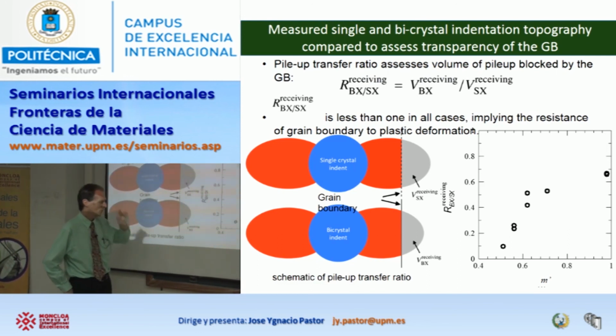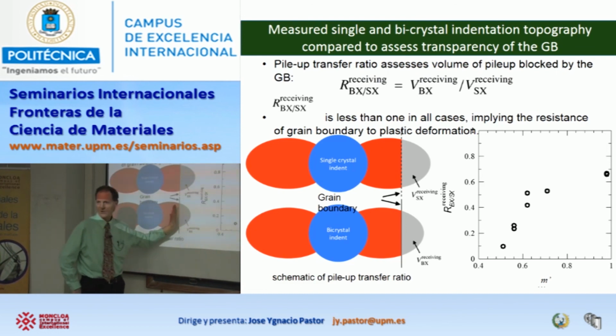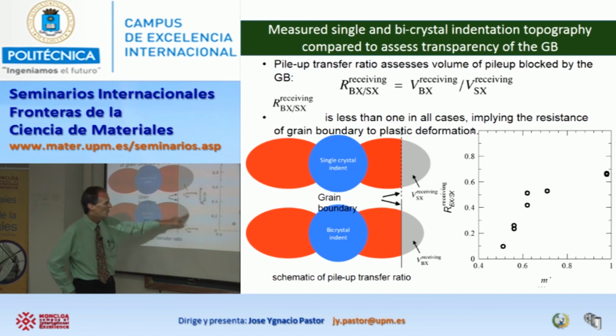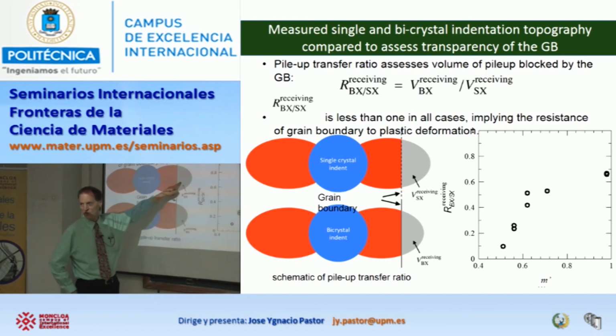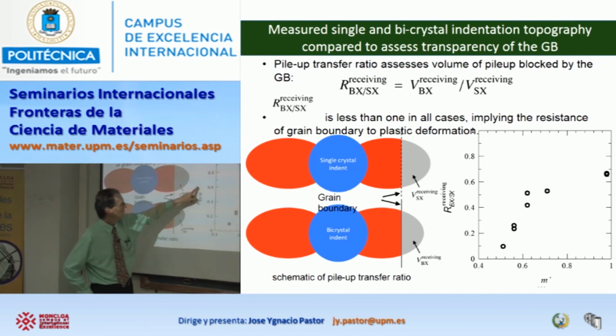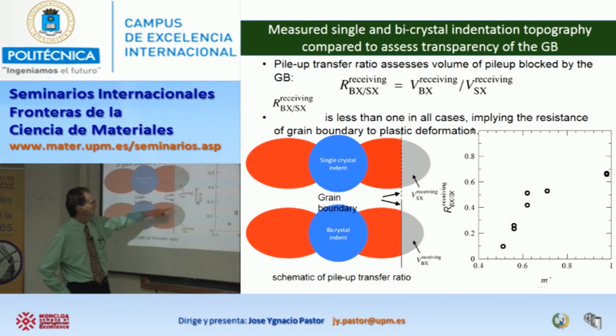That gives me a ratio. So if the grain boundary is blocking deformation, then I should get less of a pile-up bump on this side than I do in a perfect crystal where there's no boundary. So thus, I can plot a ratio of this area to that area.